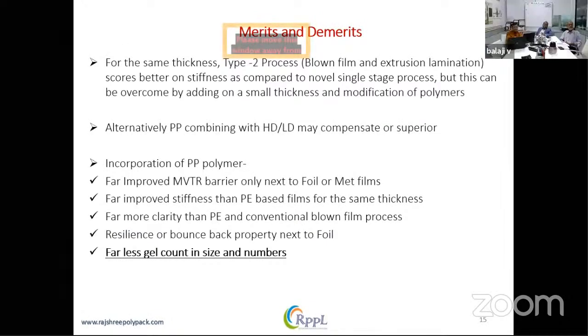As compared to the conventional, that is blown film and extrusion lamination, the direct cast line could be a little low on stiffness, we feel so. But we are very confident of overcoming the same with a small add-on thickness and modification of polymers. Alternatively, the PP combining with HDPE may compensate, could be superior. We feel that incorporation of PP polymer in the sandwich layer gives improved MVTR, improved stiffness than PE-based films, more clarity because it's produced in the cast film rather than the blown process, and resilience or bounce back could be improved. And we will have far lower gel count in size and numbers.